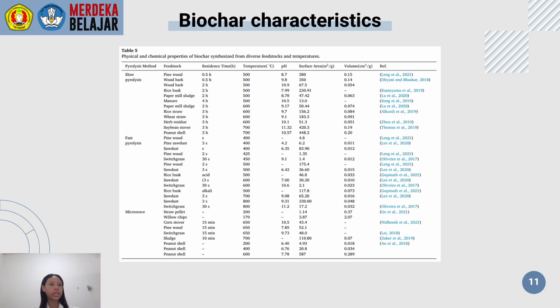Carbon stability is an important performance criterion in the process of carbon sequestration and soil fertility improvement. Surface area and nutrient content are important quality indicators in improving soil fertility. The molar ratio of hydrogen to carbon, H/C, is an important characterization measure for biochar as it indicates the degree of carbonization and stability of the materials. An H/C ratio greater than 0.7 indicates poor biochar quality and pyrolysis limitation.